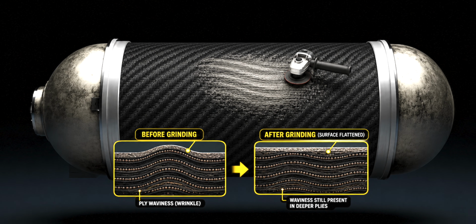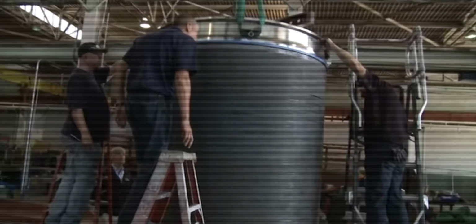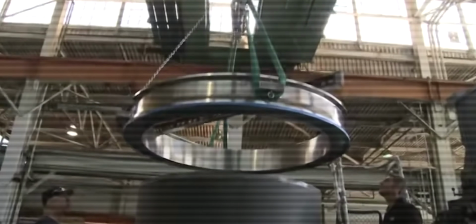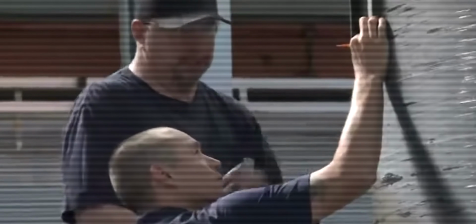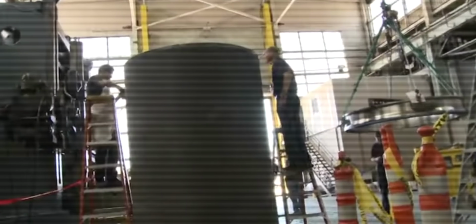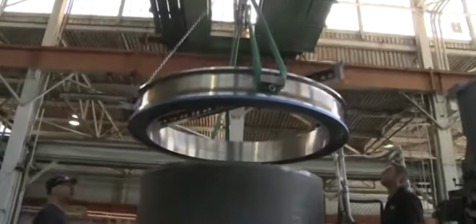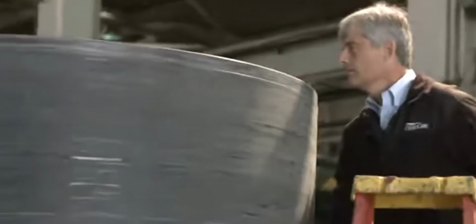Investigators also found numerous microscopic air pockets, known as voids, trapped within the epoxy resin. On average, these voids occupied about 2.7% of the laminate's volume, reducing the composite's overall strength. They also made the finished pressure hull too thick to fit properly inside the titanium interface rings. To compensate, OceanGate machined material from the outer surface of the hull, removing some of the very carbon fibers intended to withstand the immense external pressure.